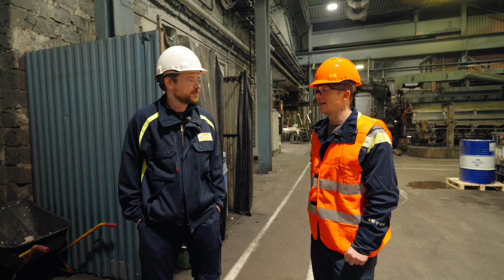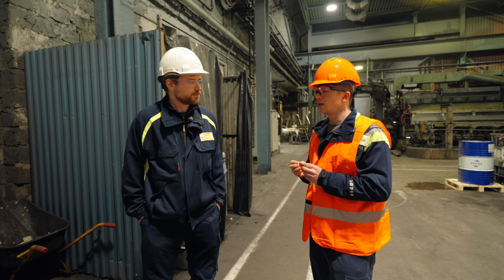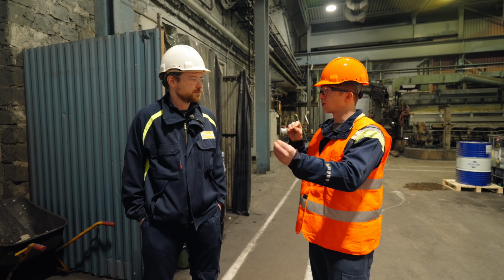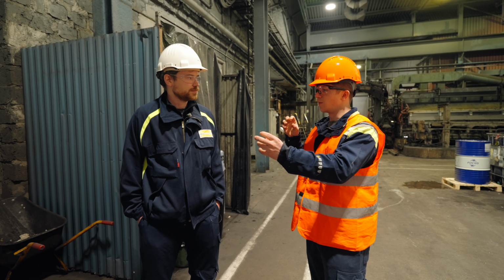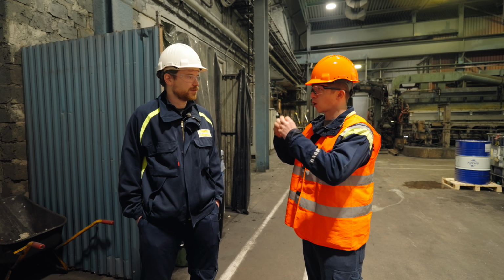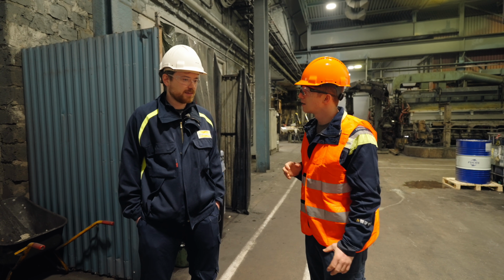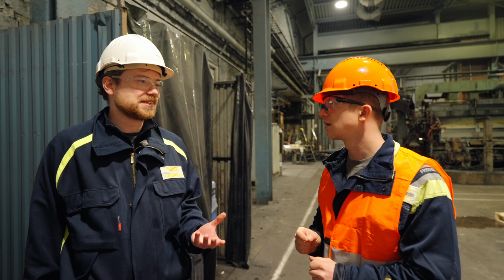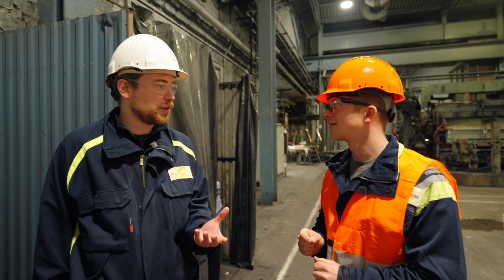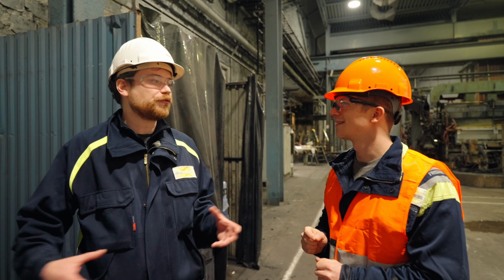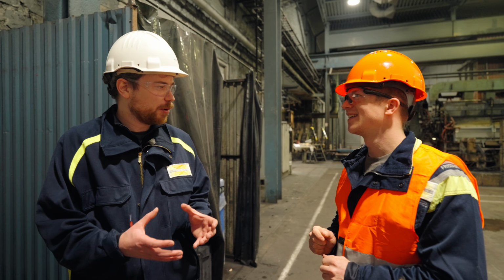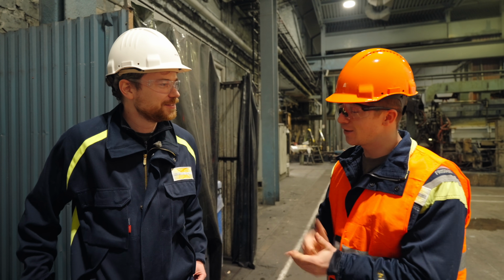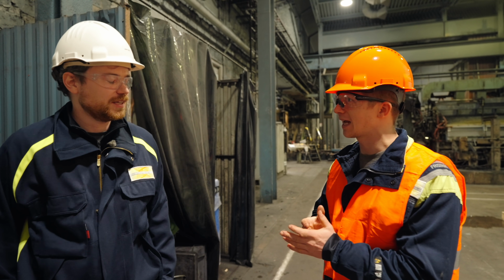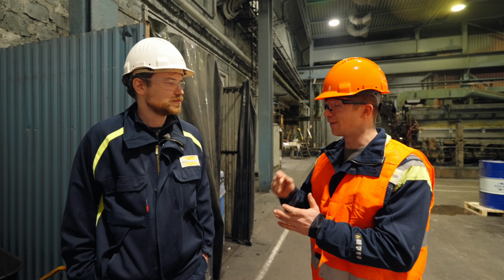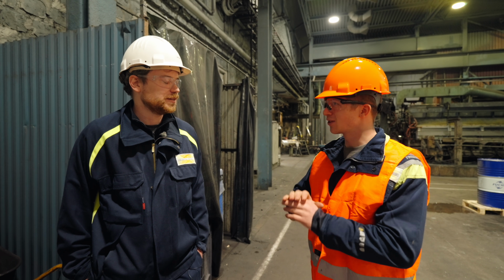Okay. So this allows you to make sure that long carbide stringers don't become a stress concentration for cracks to form. And that's perfectly correct. Basically, you are alloying the steel in such a way to get carbides. So you actually want the carbides in there. But when they clump together and form large, massive carbides within the steel, they become a problem. Okay, so it's about forming the perfect carbides thanks to these high alloying elements, but forming them the perfect size and shape every single time, the whole way through the bar.